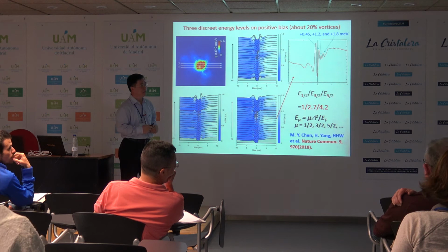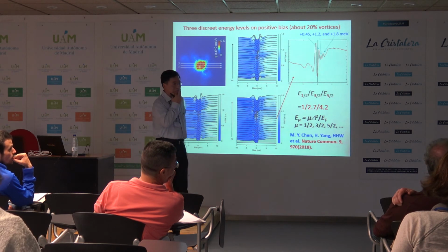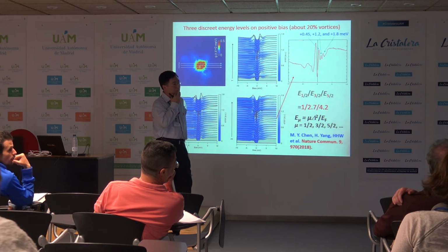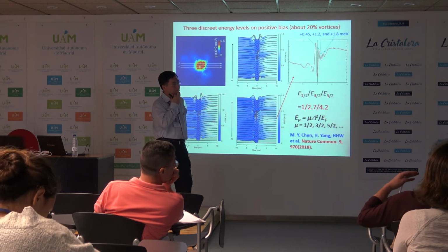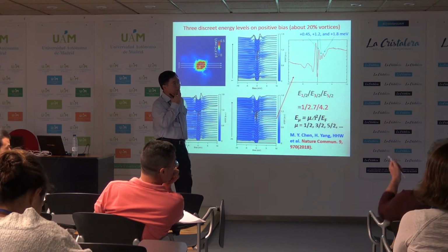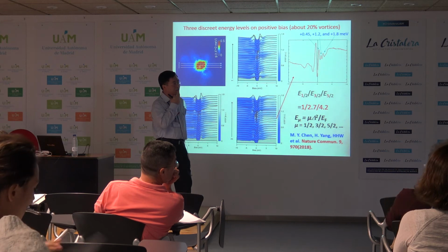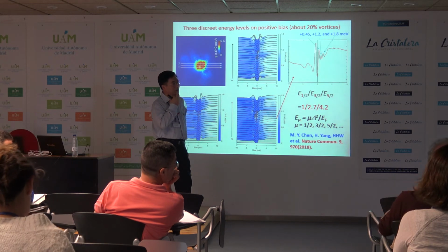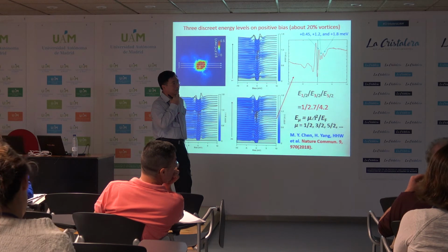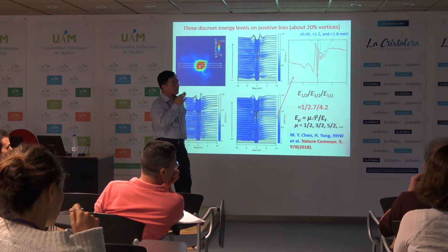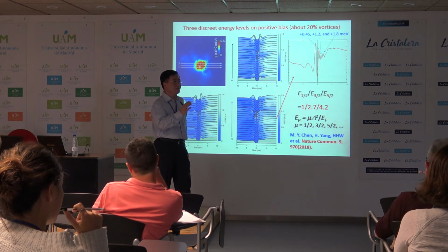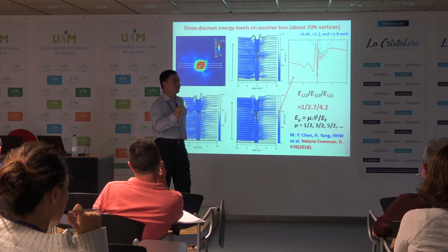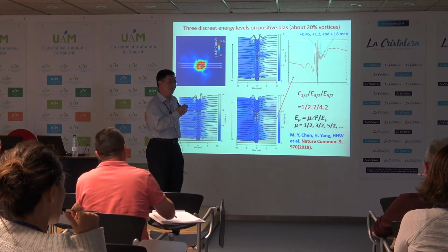No, but the vortex bound states are asymmetric. Why is it not particle-hole symmetric? Because the background band structure is particle-hole asymmetric. But in the initial calculation, there was none. If you do the real calculation, you capture the background. Okay, so the real calculation overrides that effect completely. Yes. If this vortex has nothing to do with topology, then it should be the same.